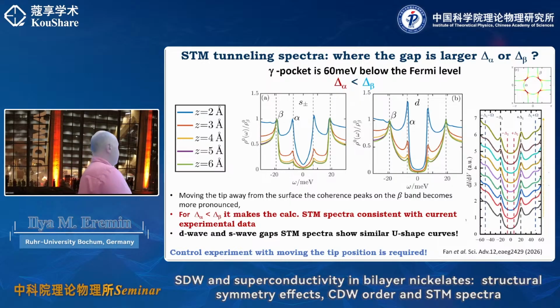But again, even in this case, it's very difficult to distinguish between accidental S plus minus with accidental nodes and the D wave, because in the D wave case, you can have a completely flat region here. Whereas in the case of S plus minus, because of accidental nodes, you still see a V-like shape. So again, the low energy, low bias behavior of the STM can be, in this case, misleading. But what is interesting is that if you are able to shift the position of the tip and do measurements at different positions, it can provide you momentum selective information.